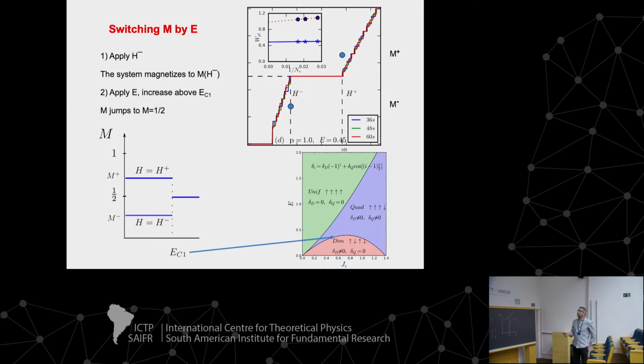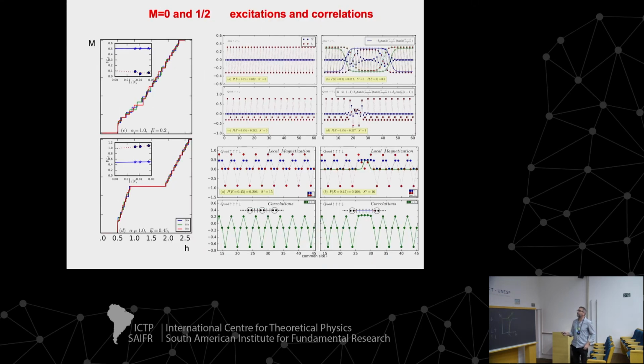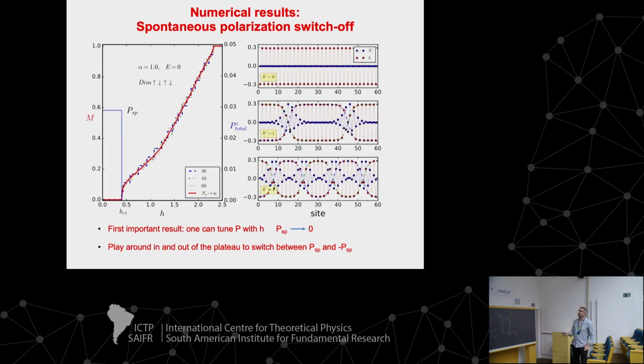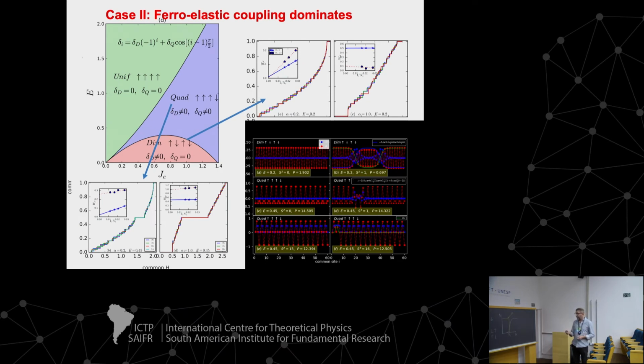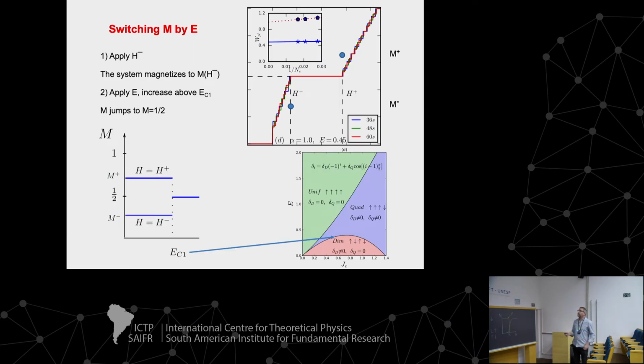Okay, so maybe I will say a few words. One thing I discussed was this jump of P. So this is varying electric polarization. This is a new thing with a magnetic field. So the question is whether you could do the opposite, that means varying magnetization with an electric field. And this can also be done because the magnetization curve looks like this. So you have some plateau at 1/2 here. So if you put a magnetic field to go around here, then you can go from one magnetization to another with an electric field. So this is a bit longer to explain.